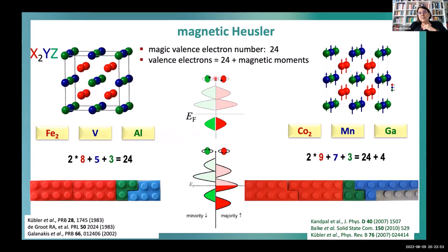This is a semiconductor because for both spin directions, this one spin direction and the other spin direction, they are fully identical. So they are diamagnetic, and they have the Fermi energy, which separates the occupied from the unoccupied states, in the middle of the gap. And so these states are also 12 in each spin direction. So it's a simple non-magnetic semiconductor. This is a good thermoelectric material.